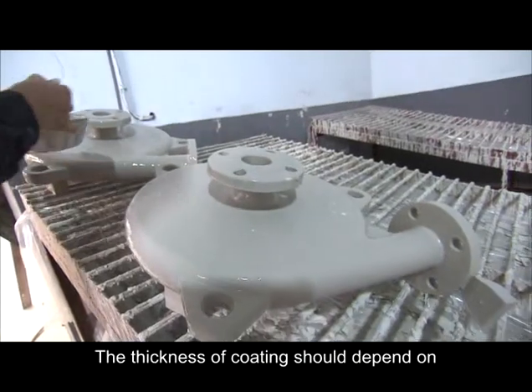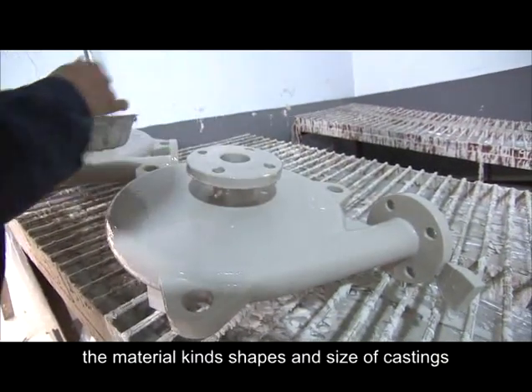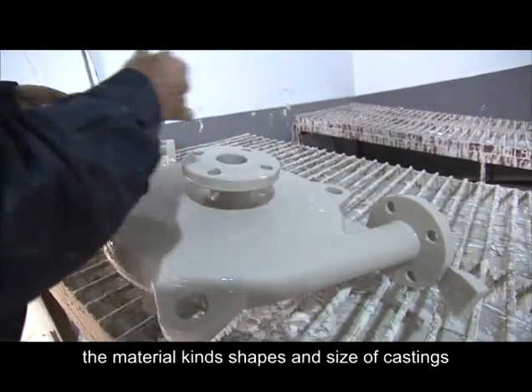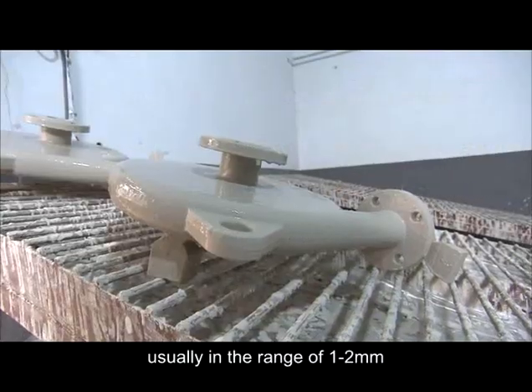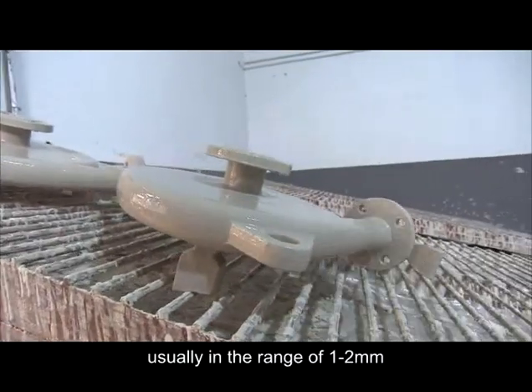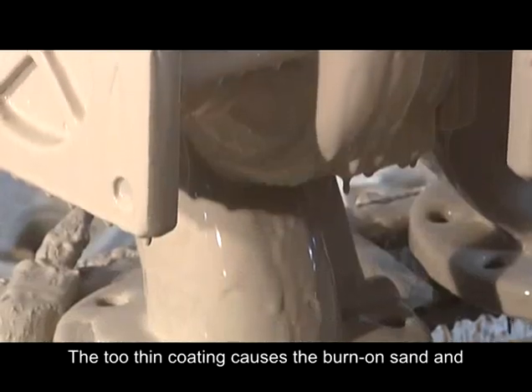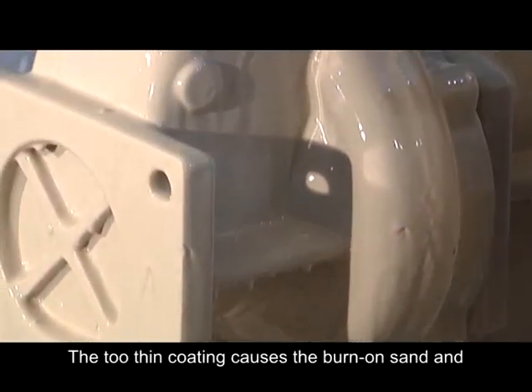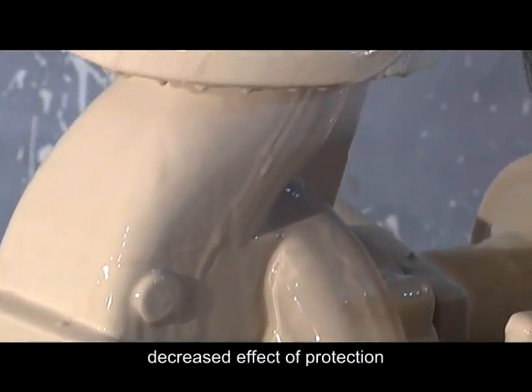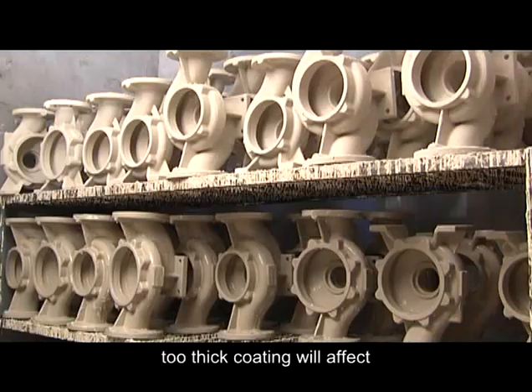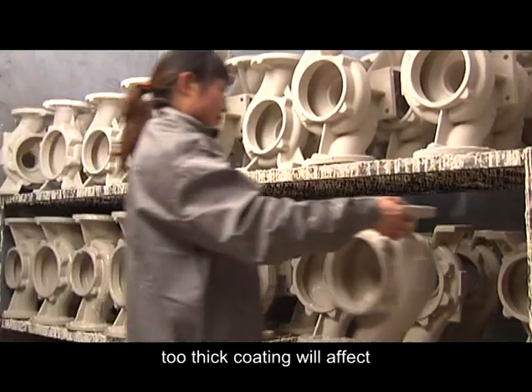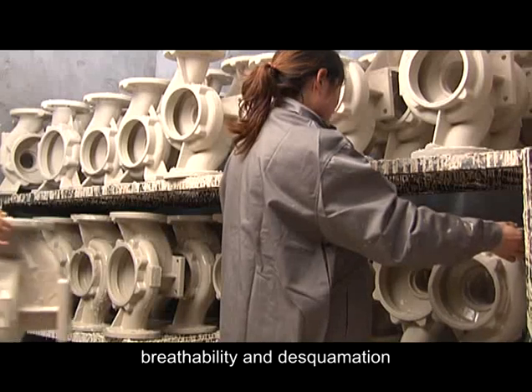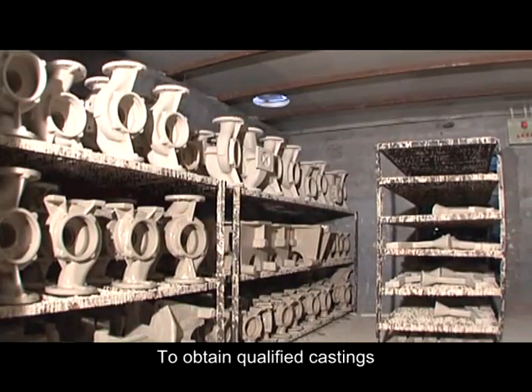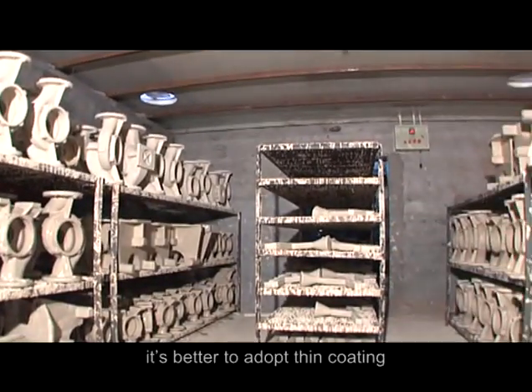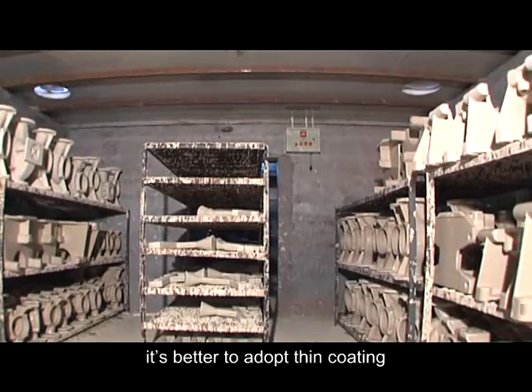The thickness of a coating should depend on the material, kind, shapes and size of castings, usually in the range of 1 to 2 mm. Too thin a coating causes burn-on sand and decreases the protective effect. Too thick a coating will affect breathability and cause desquamation. To obtain qualified castings, it's better to adopt a thin coating.